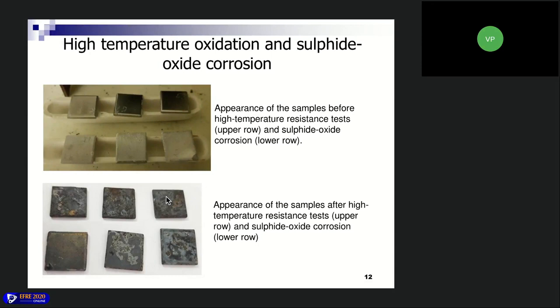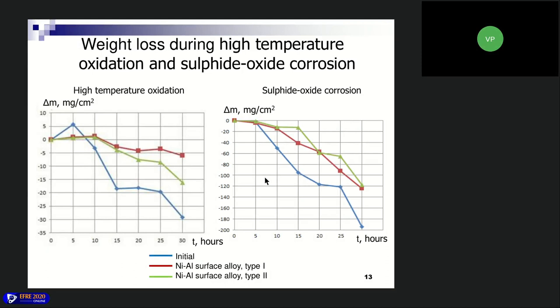And we also carried out high temperature oxidation tests and sulfide-oxide corrosion tests. For these tests, we took the samples and put them into high temperature. These 3 samples were tested for high temperature oxidation, just high temperature and air. The lower row is samples for the sulfide-oxide corrosion tests. They were covered with a salt water solution, and then they were heated together with the samples for high temperature oxidation. Here are the samples after the tests, and the next slide is the results of the measurement of mass of these samples.